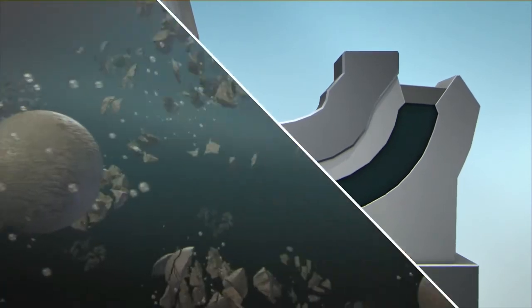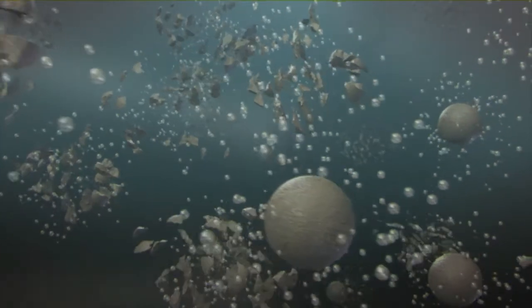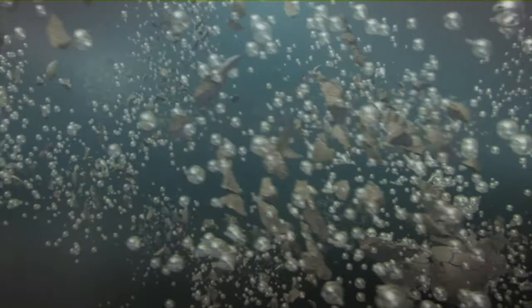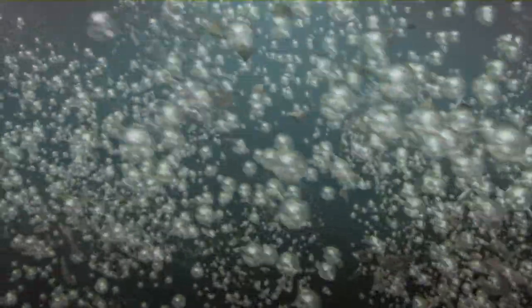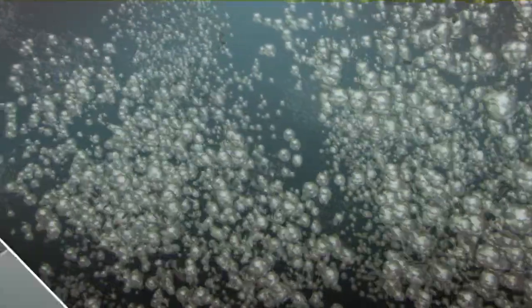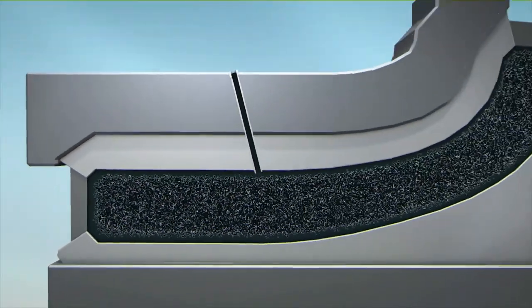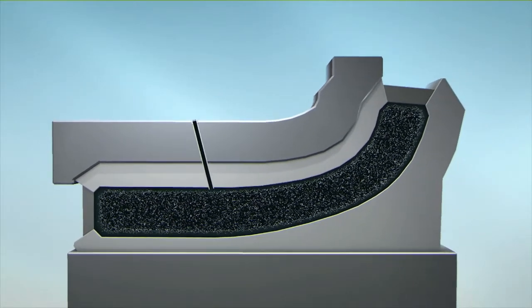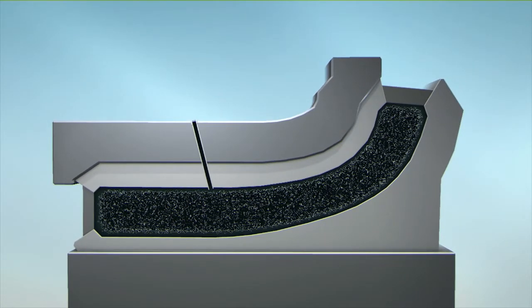outwards. The foaming and nucleating agent decomposes under heat, and an increasing number of fine gas bubbles form, which distribute themselves throughout the plastic melt and create a homogeneous foam structure inside. Finally, the mold is filled completely, but the outer skin remains undamaged. After cooling, the component is removed from the mold.